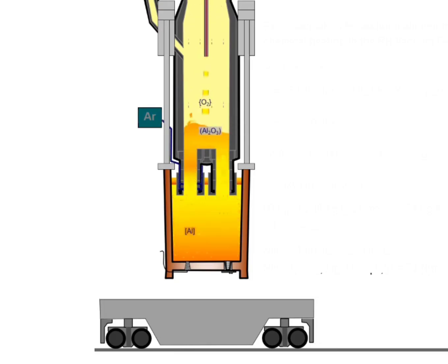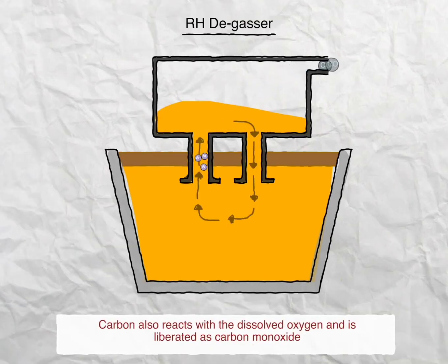Aluminium oxide formed adds to the slag, but some is retained in the melt. This can lead to unacceptable levels for tin plate grades of steel. An RH degasser vessel equipped with oxygen injection can further decarburize steel, that is, reduce carbon content within the liquid steel.